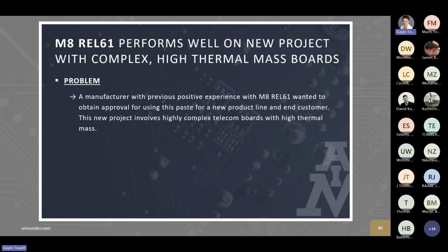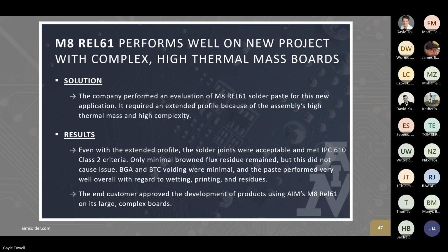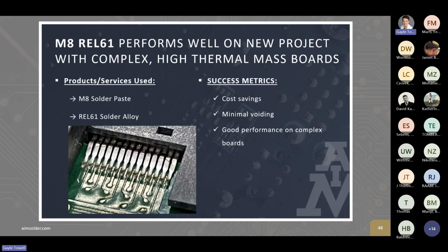In another case, M8 REL61 paste performed well on a new project that had complex high thermal mass boards. Manufacturer had previous positive experience with this alloy. They wanted to obtain approval of this paste for a new product line. So they tried it out on the new application. Did require an extended profile because of the high thermal mass and high complexity of the board. So even with the extended profile, the solder joints met the IPC criteria. Only minimal brown flux residue remained, did not cause issues. Voiding was minimal, and the paste performed very well overall. And customer approved the use of the paste for development. So they saw cost savings, they saw minimal voiding, and good performance even on a complex board.